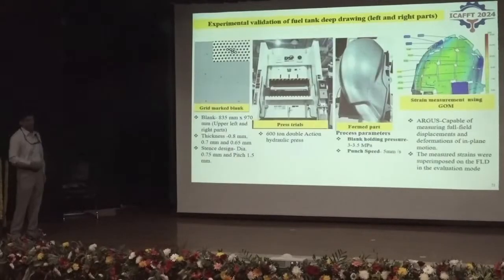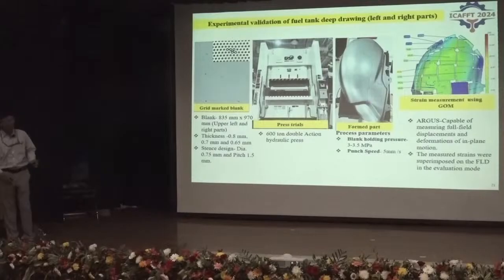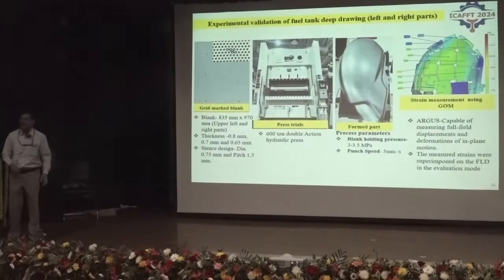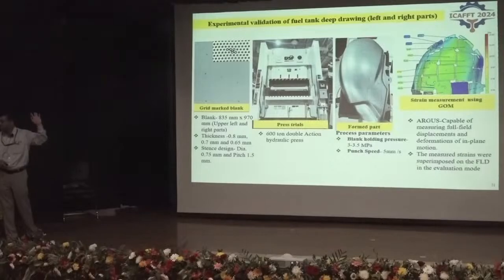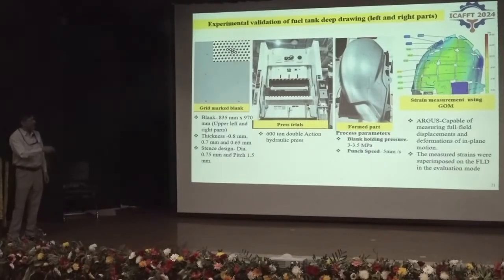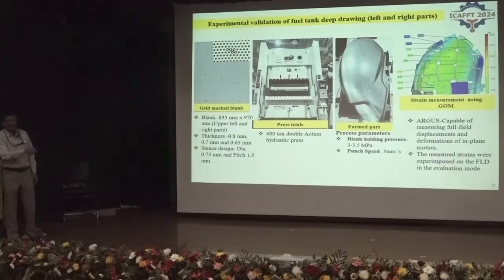can be manufactured. So then with these new thicknesses and the new grades, we have carried out the actual fuel tank manufacturing in the industry. Okay, so you can see a 600-ton double action hydraulic press has been used. All this work has been done in the NCR region, and we have used an advanced strain measurement technique called GOM to measure the strains on the deformed fuel tank parts.